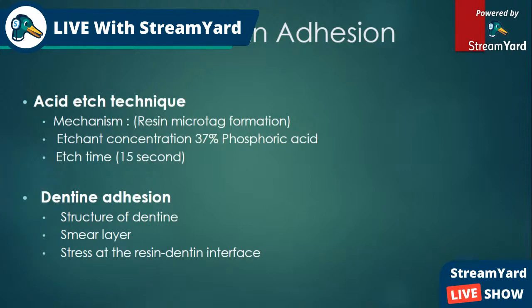And the reason you cannot use beyond 50% phosphoric acid is that it will form a monocalcium phosphate layer, which is quite difficult to remove. So if you are using more than 50% phosphoric acid to etch the enamel or dentin, it will lead to the formation of a layer thicker than the smear layer itself, and it will be quite hard to get it off.